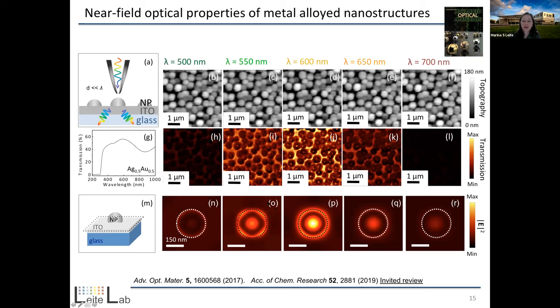What you can see here is that we start seeing the quadrupole signature of our localized surface plasmon resonance. At 600 nanometers, we are really at resonance, where we see a very high field enhancement around and underneath the particle. Just to clarify, even though I'm showing you a plane view, what we're seeing is the result of a monitor that we added just underneath the metallic nanoparticles, in the ITO layer that we have.